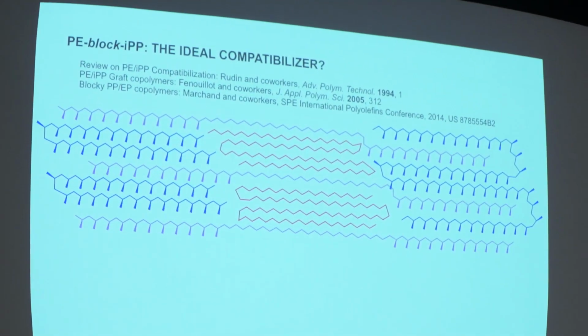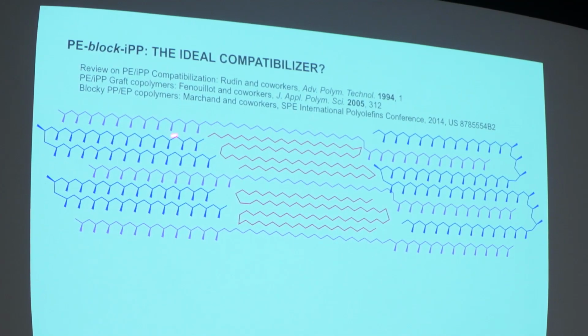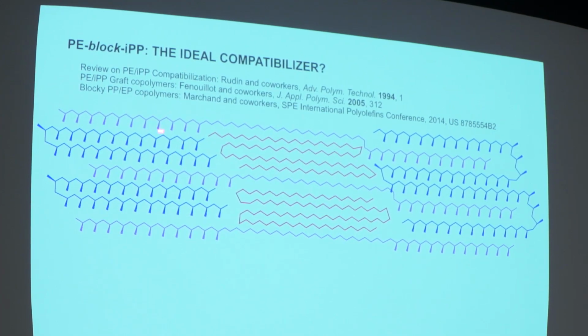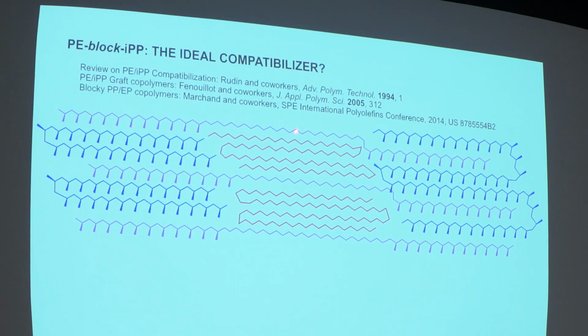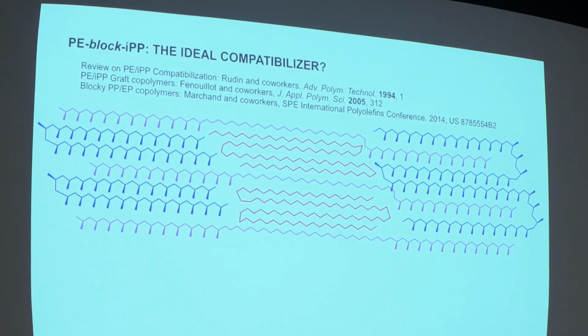The molecule that we thought would be the perfect would be a block copolymer of polypropylene and polyethylene, with the idea you would have these regions of polypropylene. And if you have a molecule where you have polypropylene and then you tie it together with polyethylene, and then you maybe have another block of polypropylene, at the interface of these macrophase separated materials, you would then be gluing those interfaces together. And instead of being able to rip it apart, almost like a perforated polymer, you would be gluing all these things together.